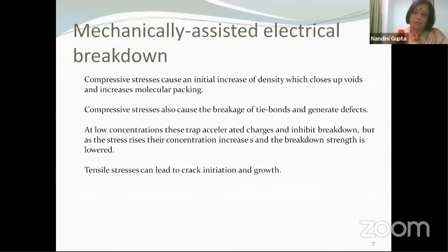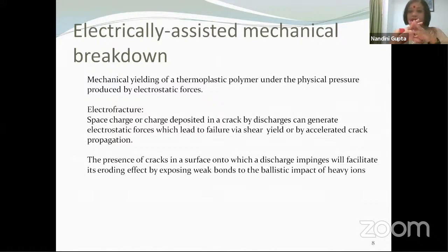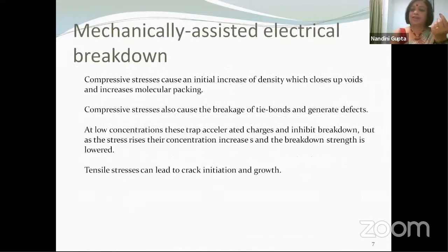Now, when you talk about breakdown through degradation, what kind of breakdown are we talking about? Broadly, we can divide the breakdown into two classes. One is mechanically assisted electrical breakdown. When you have compressive stresses, the material tends to contract. As a result, any voids that might be present might become smaller in size. Molecular packing may increase. And as I told you, molecular packing is something that we want because that increases the specific density. So if you increase the molecular packing, you have less free volume. So you may be happy with this kind of situation. So yes, sometimes the stresses do things that are desirable, but most of the time that is not the case.